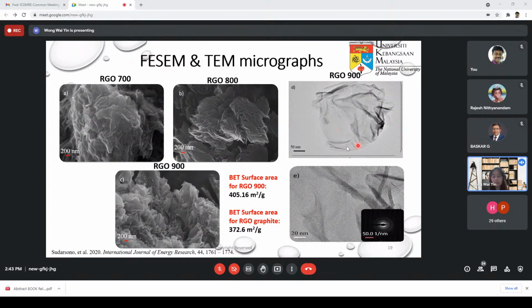You can see that it's a sheet-like structure, and also the SAED analysis shows that it's a polycrystalline structure, indicating that the graphene, the reduced graphene oxide that we obtain, is actually in the form of few-layer RGO, not a single layer RGO. Okay, and interestingly, we can see this. The BET surface area for this RGO 900 is higher than that prepared in-house by using the graphite.